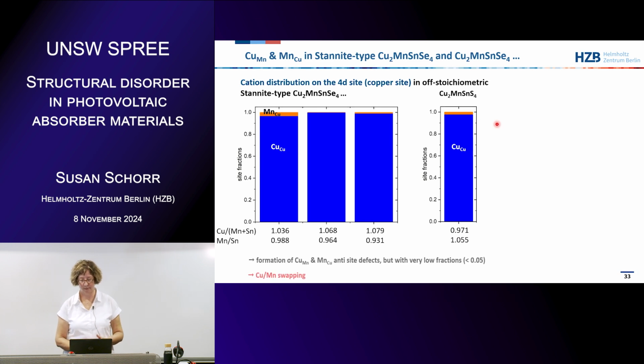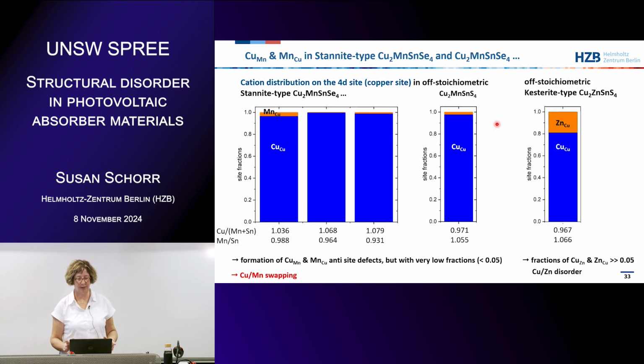Just to compare the situation with copper zinc tin sulfide, this is the amount of zinc on copper we get, and this is the copper zinc disorder. Here it's much less. It's less than 5% of the site that is occupied by manganese on copper or copper on manganese. And that's why we do not call this disorder, we call it swapping, because we found in another paper about a totally different material that they call antisites with a fraction lower than 5% swapping, to distinguish from fractions much higher than 5%, which is disorder.